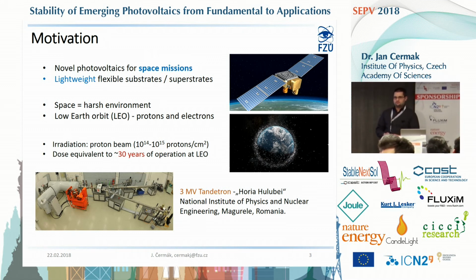Obviously, we did not send anything into the universe. Instead, the colleagues in Romania irradiated the samples with protons in an accelerator, with a dose equivalent to 30 years of operation at Earth orbit. Similar tests have been performed on finished perovskite solar cells in the last one or two years. However, such an experiment, from our point of view, is very difficult in such a configuration. It's difficult to identify which particular part of the solar cell, which layer, is responsible for the observed phenomena. Therefore, we started to study the materials individually. We started with the substrate materials.